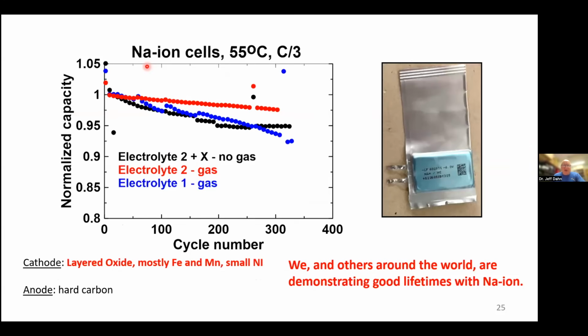Just to show you some performance data for sodium ion cells, this is at 55 degrees C, which is very aggressive and causes cells to die rapidly, running at a 3-hour charge and a 3-hour discharge. We started working on sodium ion cells, and the first electrolytes that we used, the blue, performance was okay, but the cells generated gas. And then we switched to another electrolyte that improved the performance, but we still got gas. And then we learned if we added a special ingredient to electrolyte 2, we could eliminate the gas, and you can see that things look like they're going to go really well. So we and others around the world are demonstrating good lifetimes with sodium ion, and a number of Chinese companies and also a company from India have announced commercialization plans for sodium ion.